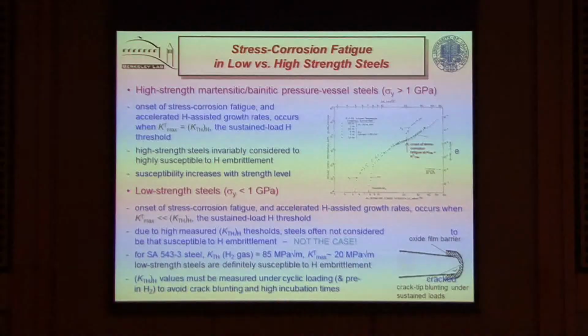And in blunting, it forms an oxide film, and it gets more difficult for hydrogen to penetrate that. But of course, that's a rather artificial situation, because in reality, there's always cyclic loading. And the cyclic loading then keeps those cracks sharp and enables the same phenomenon to take place as you would see in a high-strength steel.